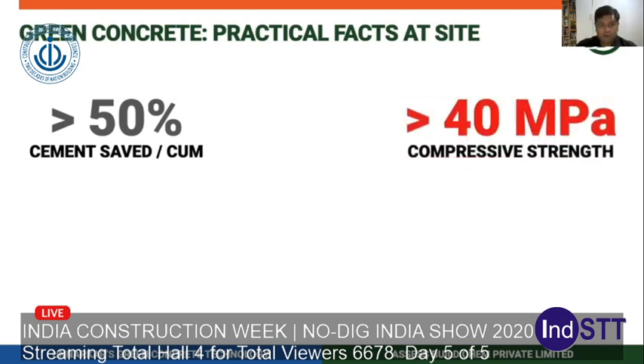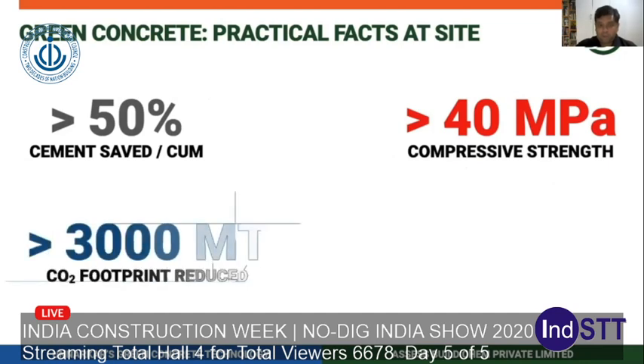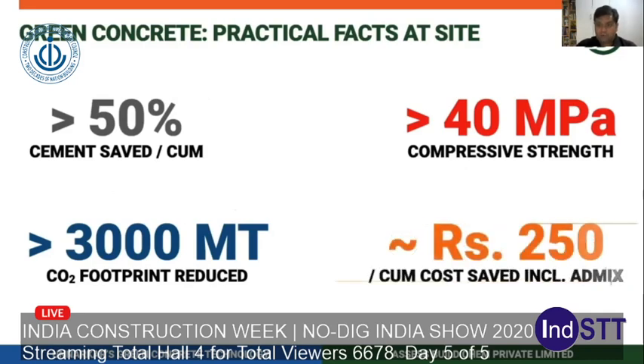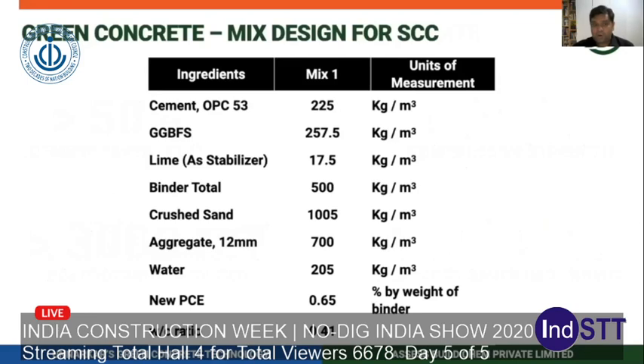So overall, we saved almost 50% of cement per cubic meter, which is almost about 200 kgs of OPC. The strengths were consistently good, over 40 MPa, so strength was not a big criterion. Over 3,000 metric tons of carbon dioxide was reduced because that was the volume of cement which we did not use. And all in all, including the cost of admixtures, we ended up saving almost about 250 rupees per cubic meter. So the next question was, could we make SCC out of it?